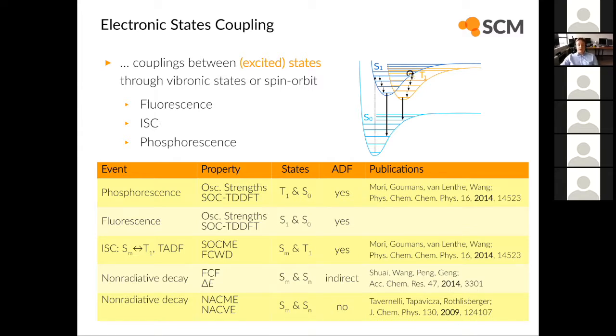transform itself. So basically, usually one has an intersystem crossing, which is frequently exploited in OLED materials, which is basically to go from the singlet into the triplet state. One can have fluorescent effects and phosphorescent effects. These are the decays upon emission of radiation from the singlet and triplet states, respectively.